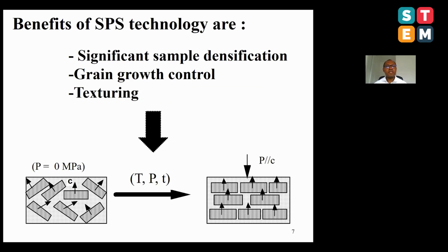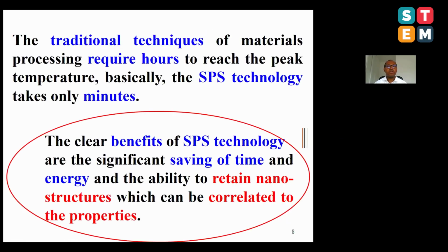Some benefits of this spark plasma sintering, named SPS technology, are significant sample densification, grain growth control, and also you can induce some grain alignment. But the main condition here is to have lamellar structure materials, or some layer-shaped compound, where by applying pressure at high temperature, you should be able to control the grain alignment between grains. Compared to the traditional technique, which requires an hour to reach the peak temperature, SPS needs only a few minutes.